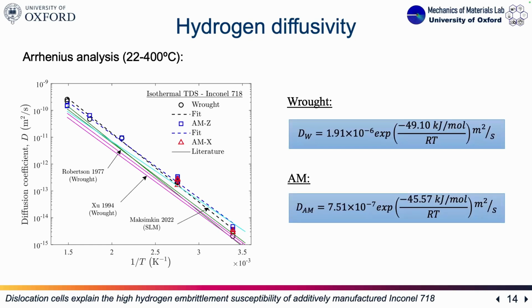And again here, as we could see in the trapping analysis, the binding energies were a little bit smaller in the additive condition. We can see the energy associated with activation of diffusion in the lattice is a bit smaller as well than in the wrought condition.